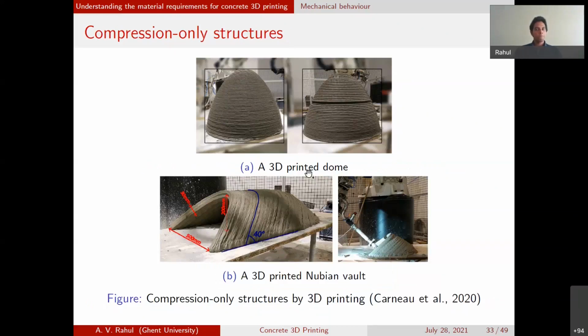The other method that has been demonstrated, or that we can look at, is compression-only structures. For example, a Nubian vault or a dome structure. In fact, if you look at how concrete structures have evolved, if you look at times before reinforced concrete, especially the historic monuments, many of them utilize domes and arch shapes in regions where you would need to carry tensile stresses if you go for linear elements. So this is one of the techniques that can be used, and because you don't require formwork, these elements can be made quite easily in concrete 3D printing.